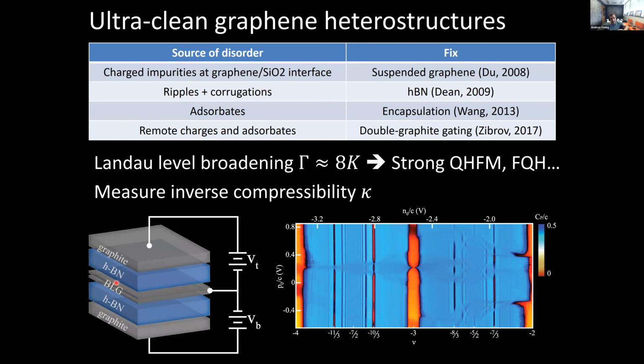It actually turns out that these interfaces between graphene and hexagonal boron nitride have this wonderful kind of self-cleaning quality, where they will form an atomically sharp interface, and as you manipulate them, any trapped hydrocarbons will actually move to the boundary and then don't get back in once that interface seals. So you can make very clean interfaces.